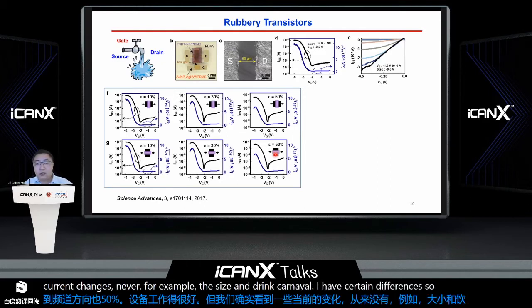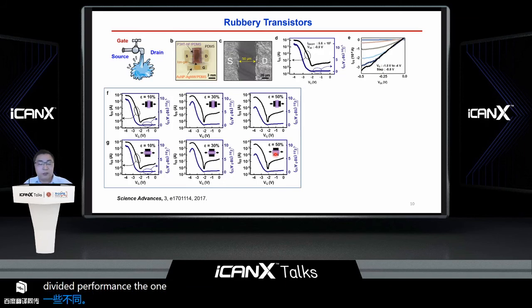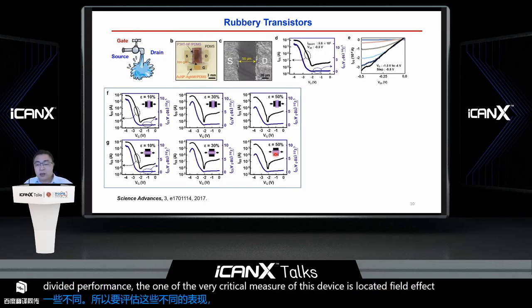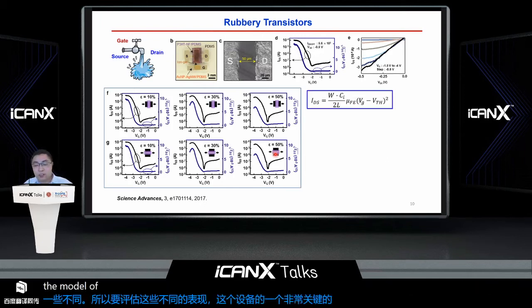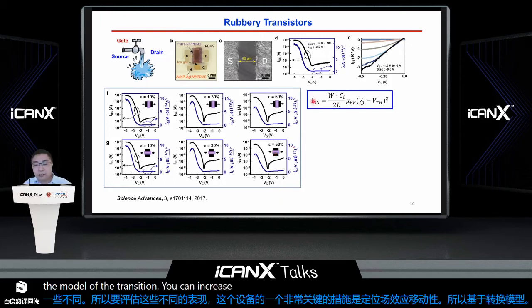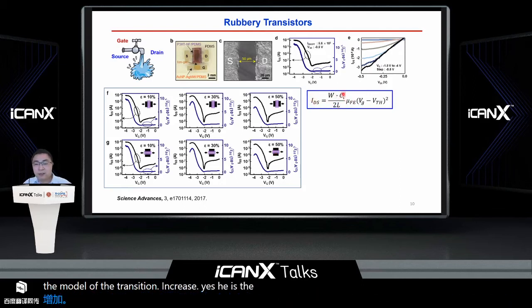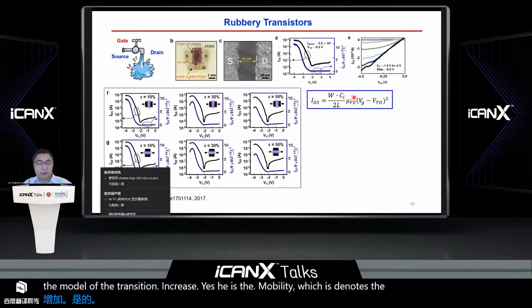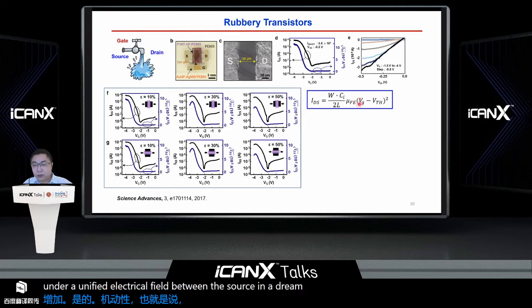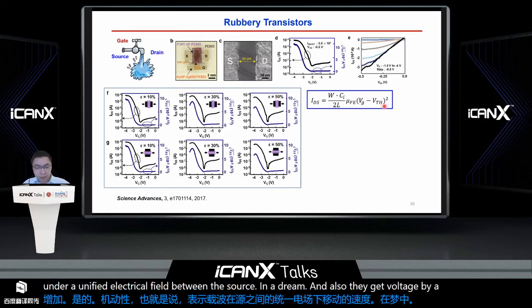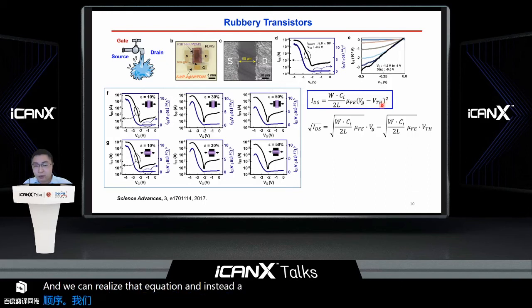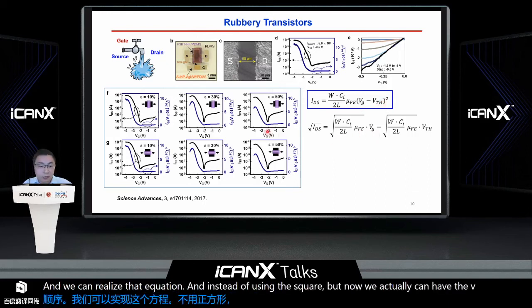To evaluate device performance, one very critical measure is the field effect mobility. Based on the capacitor model of the transistor, we can write the equation of IDS as a factor of the geometry of the transistor and the gate capacitor, times the mobility, which denotes how fast the carriers move under a unified electrical field between the source and the drain, and the gate voltage to the second order. We can rewrite this equation, and instead of using VG squared, we can have VG, which we plot in this blue curve right here.